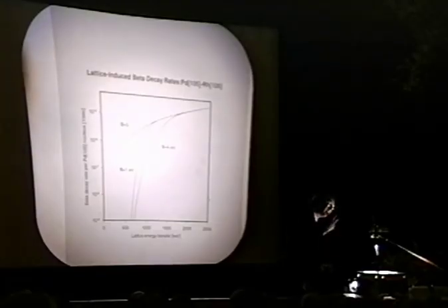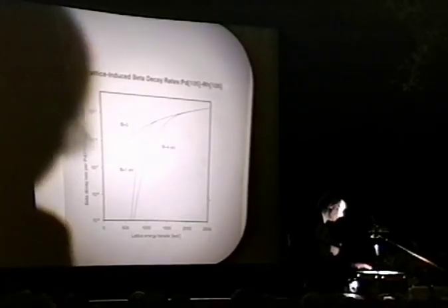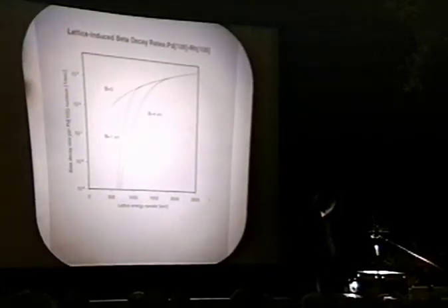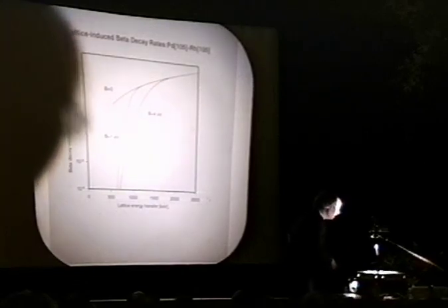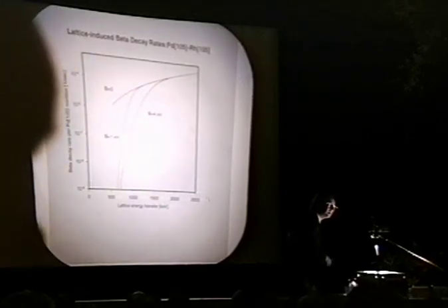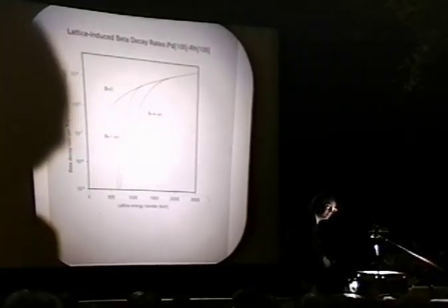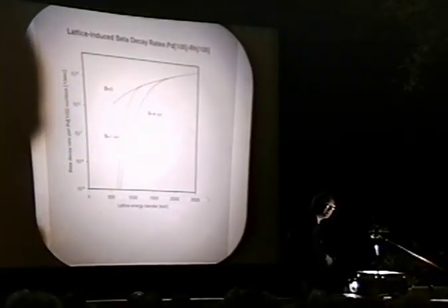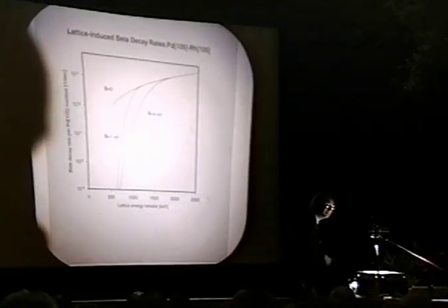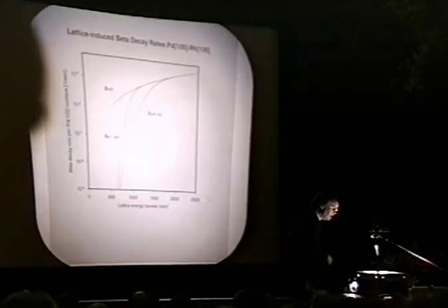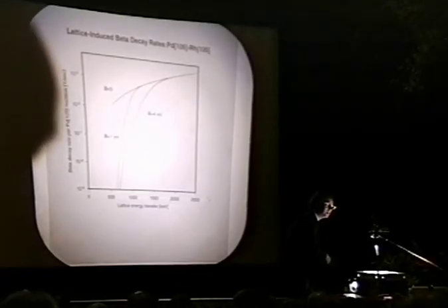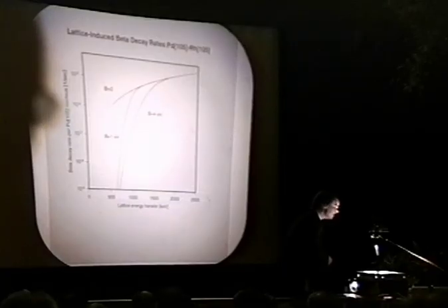Assuming you've got an arc and you've got a whole excited lattice, on the axis here is lattice energy transfer. If you believe that there are no effects of the deuterium on the vacancy energy, you only need 4 volts or so to dislodge a palladium nucleus. According to Fukai, and some experiments done at MIT in this area, in fully loaded palladium deuteride you can actually have vacancies move at energies closer to 1 electron volt, according to the vacancy diffusion data that we've taken.